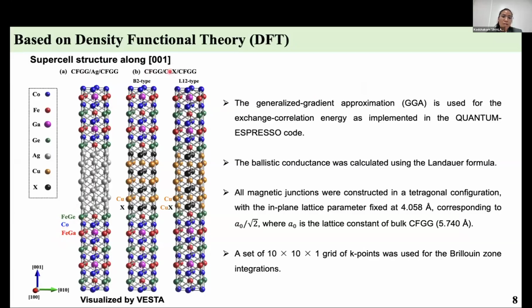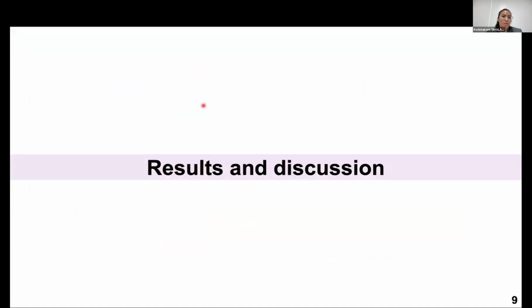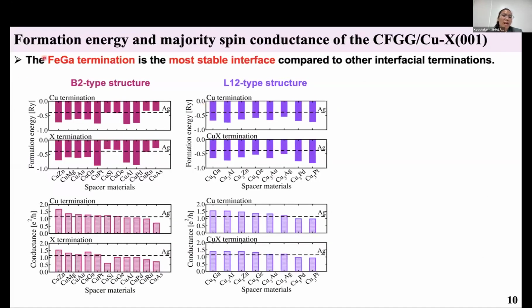For the Cu-X spacer materials, the interfacial termination depends on their structure. For the Cu and X termination, it is for the B2 type structure. So Cu and Cu-X termination for L1_2 type structure. Result and discussion: we first calculated the formation energy and the majority spin conductance at the interface. So this slide shows the formation energy in the first row and the majority spin conductance in the second row, for spacer materials at the FeGa termination, which is the most stable interfacial termination compared to the others.